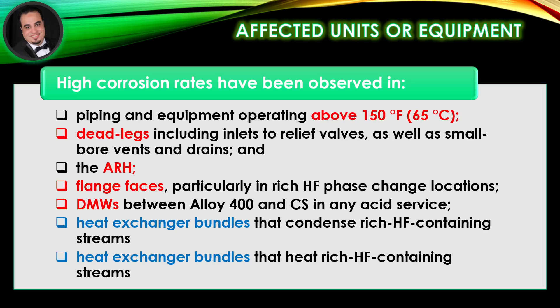High corrosion rates are also observed in dead legs including inlets to relief valves, as well as small bore vents and drains, and the acid relief header, flange faces particularly in rich hydrofluoric phase change locations, dissimilar metal welds between Alloy 400 and carbon steel in any acid service, and heat exchanger bundles that condense or heat rich hydrofluoric containing streams.